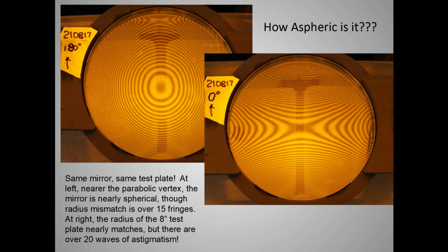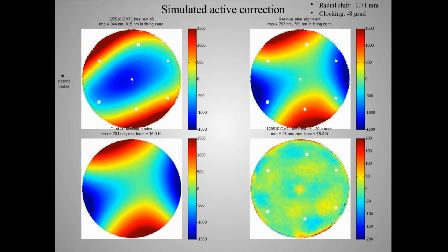Everyone who has ever made a mirror around here knows that small tools will give you a rougher surface typically. But we can do a few tricks, at least some low order stuff. This is a final measurement of GMT1, and you say, wow, that looks really crappy. Well, we're allowed to rotate it and shift it slightly, a couple millimeters in the cell, so we can shift it and rotate it slightly. And then we could end up with, this is a theoretical, I believe, this is a fit. And when you subtract, you can bend out astigmatism really easily.